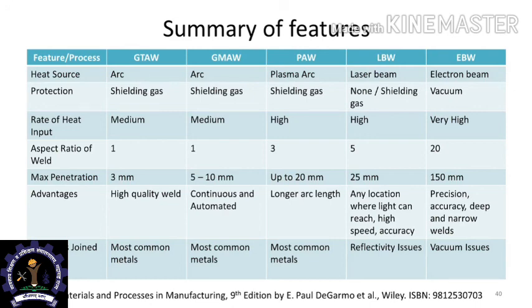And what kind of materials can be joined using EBW? Most of the materials, except those that will have a problem when you place the liquid metal in a vacuum environment. So, those materials which have elements that could vaporize very easily may face some problem in electron beam welding. Otherwise, most of the common engineering materials can be welded using electron beam welding facility. The capital cost of EBW is very high, and that is often the limiting factor why one would choose any other process over EBW. So, with this we summarize the various welding